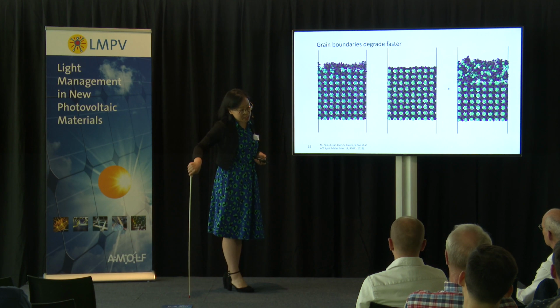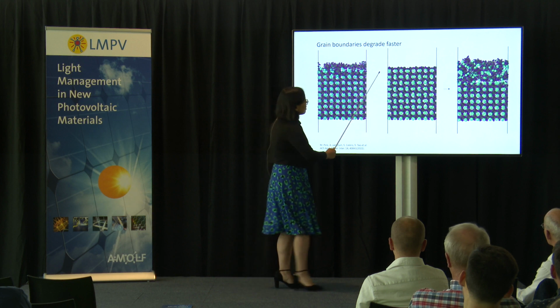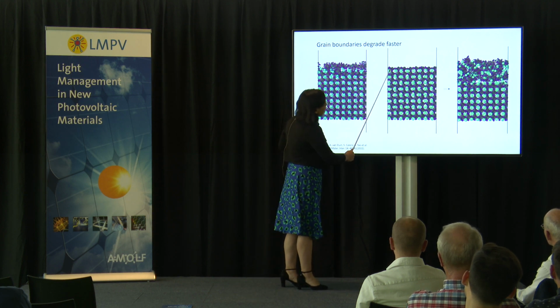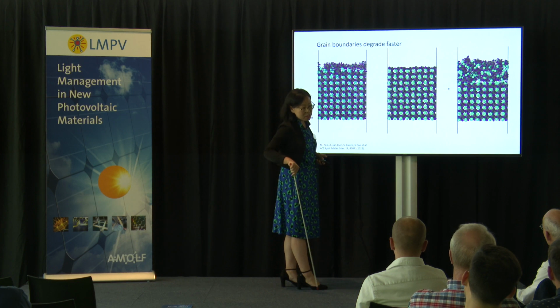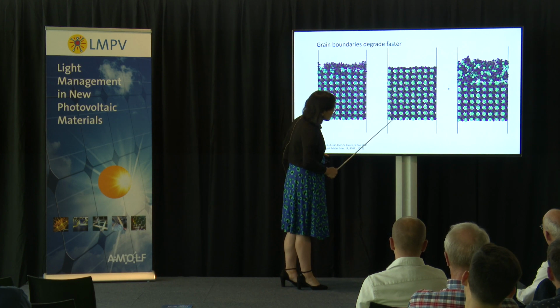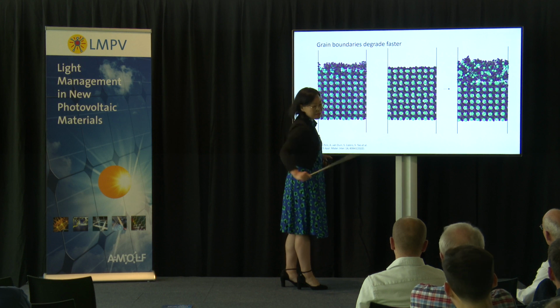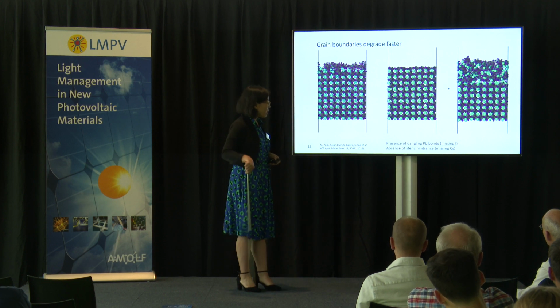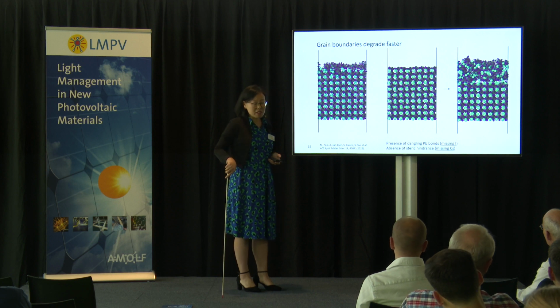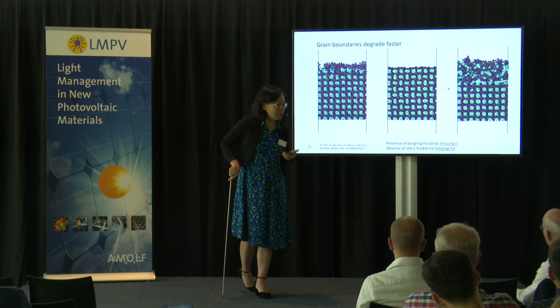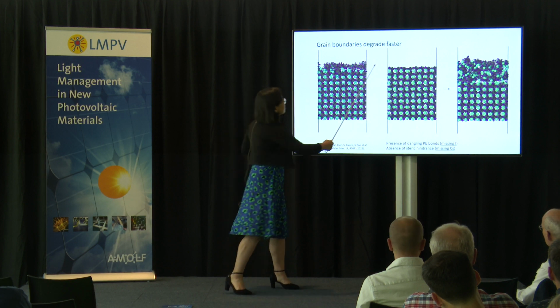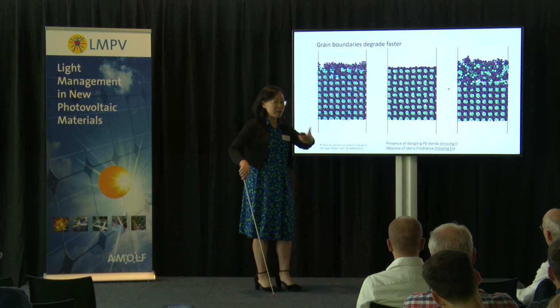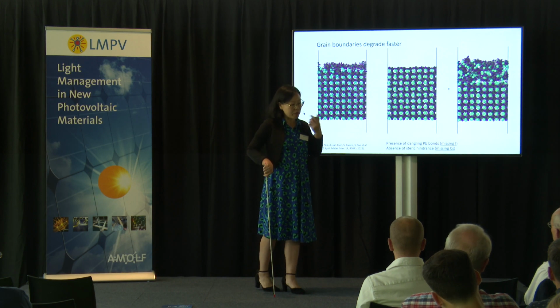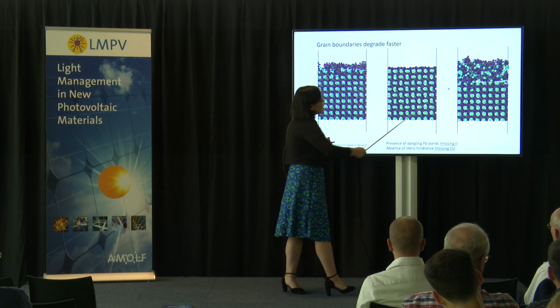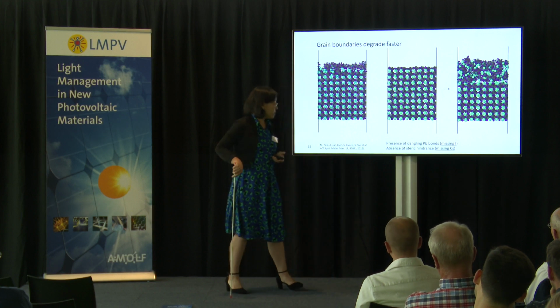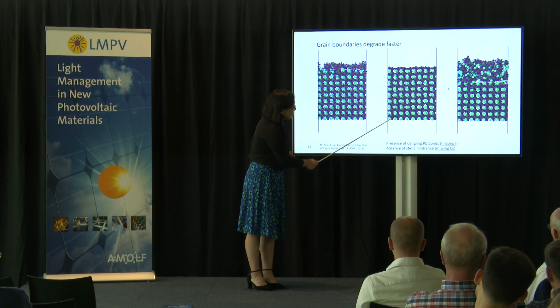What's the main difference between these 2 surfaces? If we look carefully at the top surface here, we are missing an extra iodide bond that is bonded to lead. That's one thing. Another thing is that this green sphere is a cesium ion, and we don't have that. So basically these 2 features, missing an iodide bond, which is really missing a covalent, real chemical bond, make this surface vulnerable. The iodide starts to be mobile, and there's a cascade of more dynamical processes going on, and then the lattice eventually is destroyed.